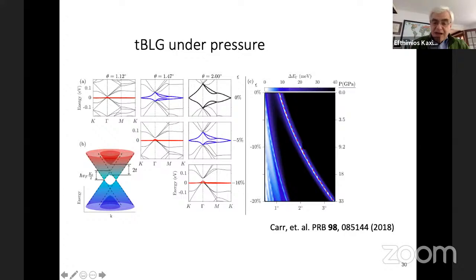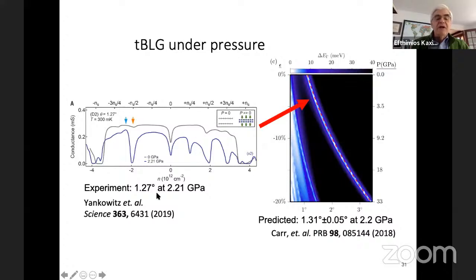So this was a prediction from our detailed theoretical analysis. And this is actually experimental work about a year later, after our prediction. So this is the prediction that we made, and this is the measurement. Experiment finds that at 1.27 degrees, that's the magic angle, you again see this large density of states and superconductivity, but at a pressure of 2.21 gigapascals, and this is extremely close to the predictions of the theory.